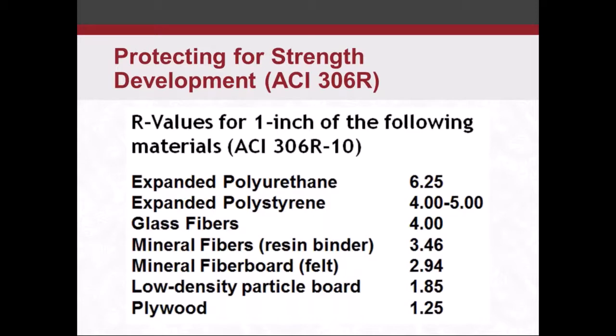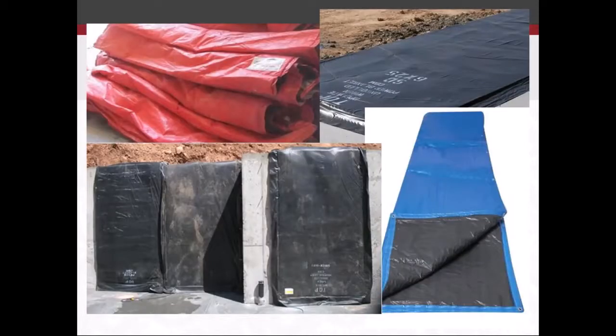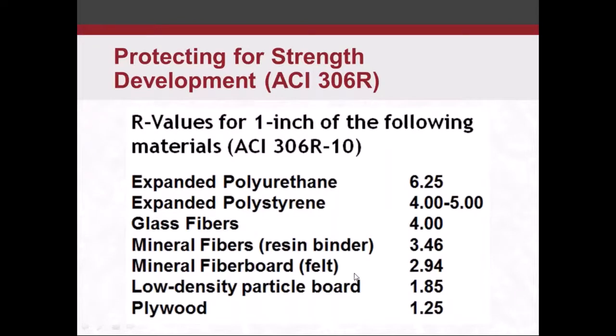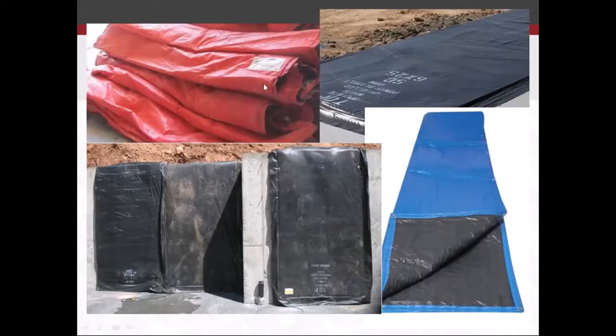One thing to note is most concrete blankets have tags on them that state what the R value is. This tag right here will tell you what the R value is. This obviously isn't 1 inch, so it's not going to have an R value of 3. Mostly mineral fibers and these fiber boards are the two most common materials inside the blankets. They're not 1 inch, so you get an R value of maybe 1 or 2 or something like that. Maybe some thicker blankets. This one's a little bit thicker. These two, these here.